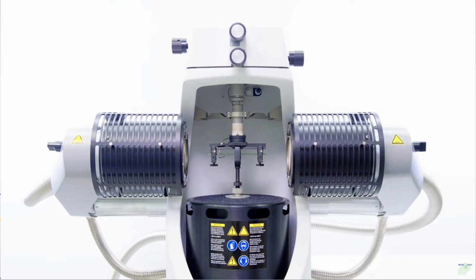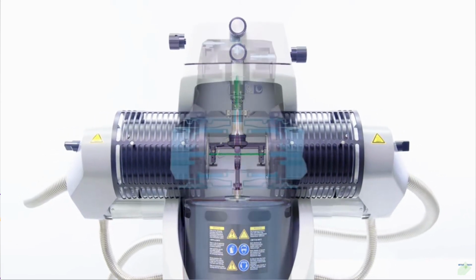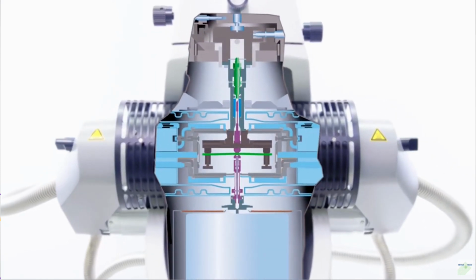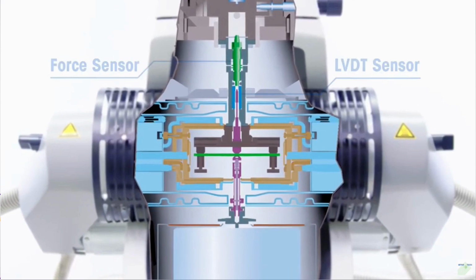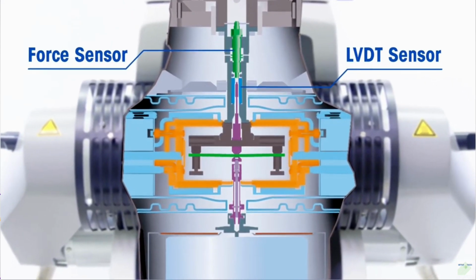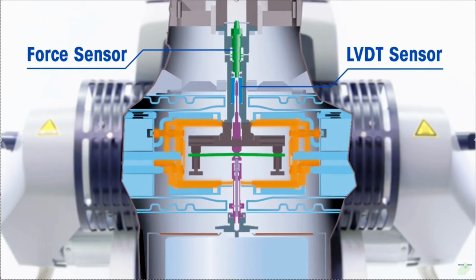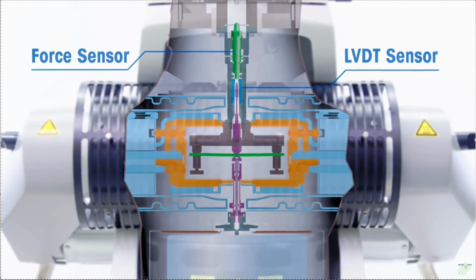So, how do we measure hysteresis? The most common method is using a dynamic mechanical analyzer, or DMA. This instrument measures the viscoelastic properties of rubber, including something called the damping factor, or tan delta. Tan delta is the ratio of energy lost, which is viscous behavior, to energy stored, which is elastic behavior. A higher tan delta means higher hysteresis. Another way to assess hysteresis is through cyclic stress-strain testing, where rubber is repeatedly deformed and the energy loss is calculated from the hysteresis loop. In tires, hysteresis is often measured indirectly by evaluating rolling resistance.